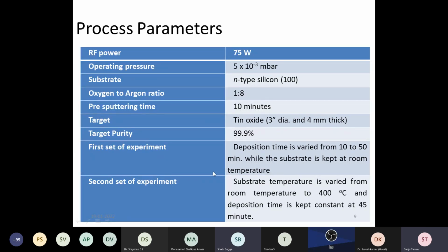Here, apart from that, we have varied two parameters. I am not showing all parameter variations, I am showing you only the two parameter variations. In the first set of experiments, deposition time was varied from 10 to 50 minutes, while substrate temperature was kept constant. First, we deposit these films, then optimize it, and then we fix what deposition time we have to keep. And in the second set of experiments, using that optimized deposition time, we deposit the film by varying the substrate temperature from room temperature to 400 degrees centigrade.